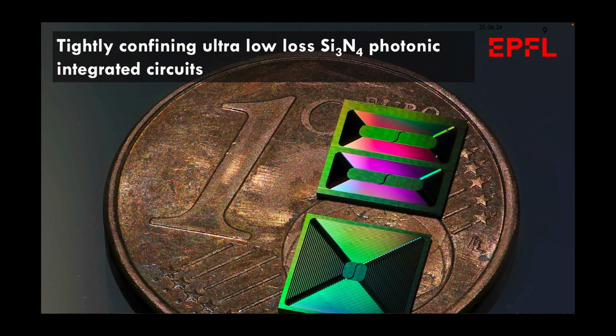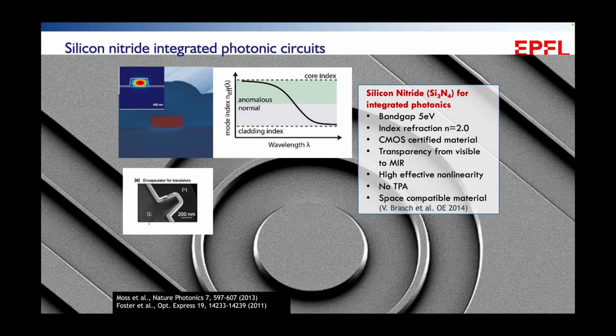So how can this be done? The first step is that we moved to a material called silicon nitride. Silicon nitride is very well known in the semiconductor industry. It's used as an etch stop layer or capping layer. It's also used as a stressor layer for silicon transistors, because you can deposit it with very high intrinsic stress, like a gigapascal, using chemical vapor deposition. Traditionally in the semiconductor industry, these films were employed at the level of tens to 100 nanometers, and if you go beyond 100 nanometers, these materials crack. That's why it has been very challenging to create tightly confining integrated photonic circuits based on these materials for many years.